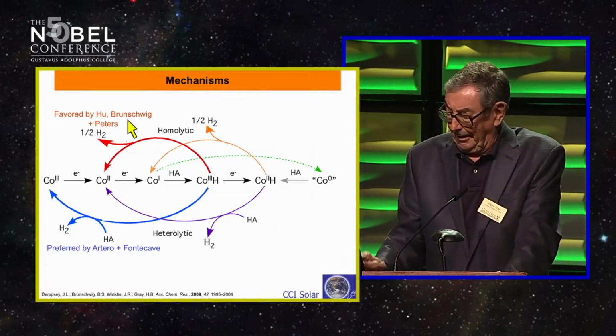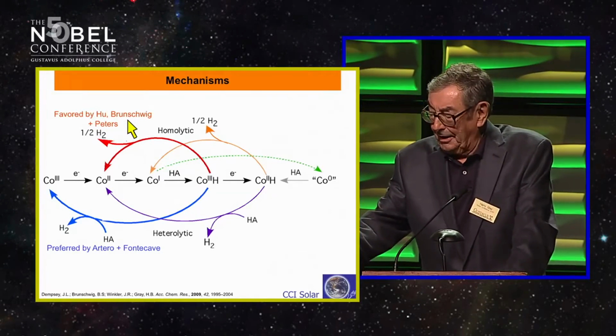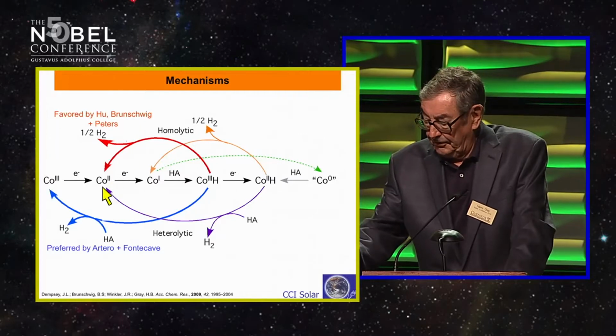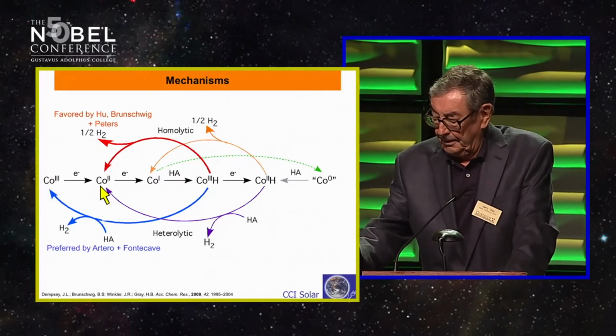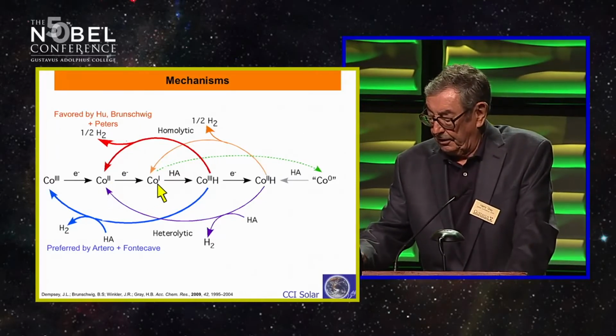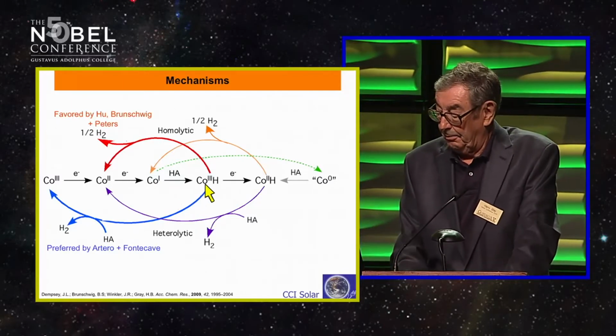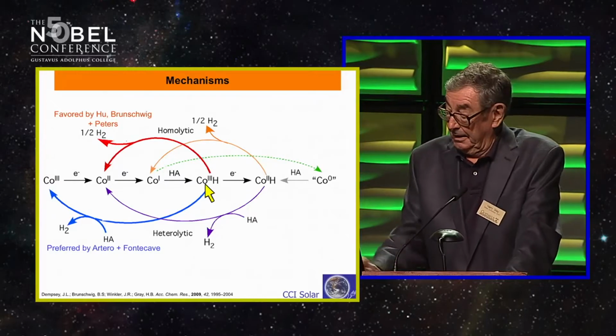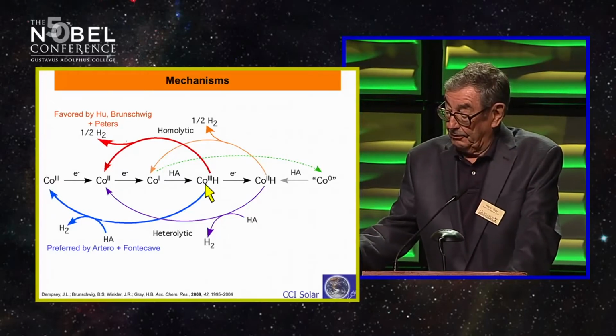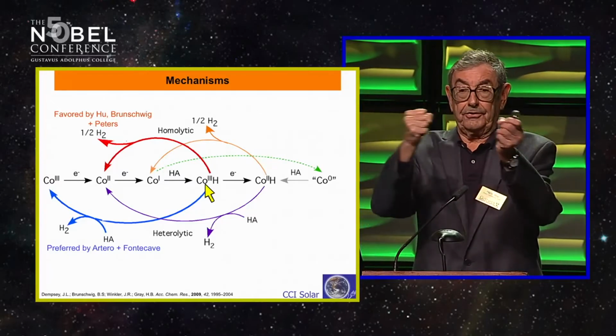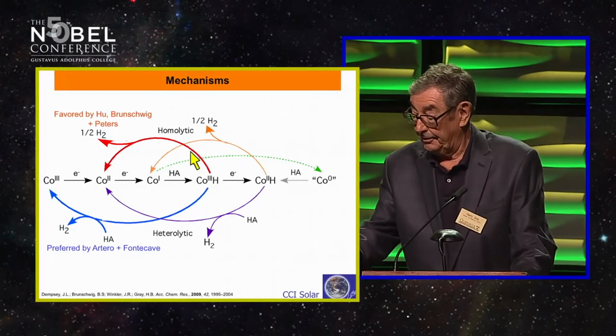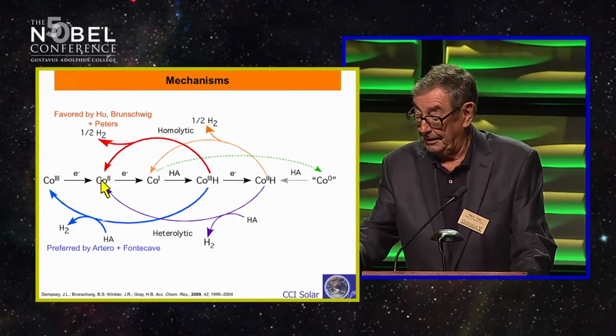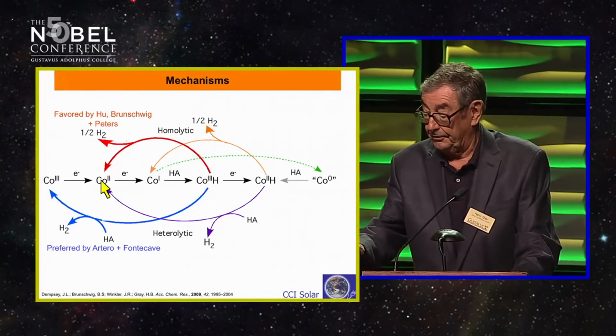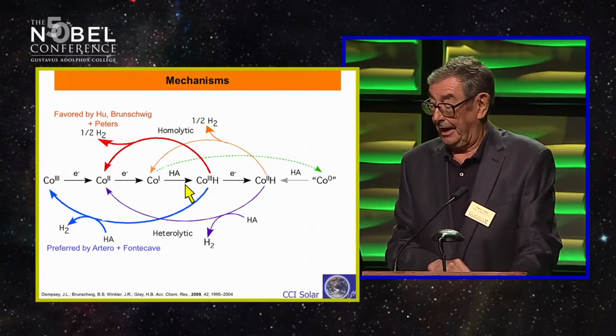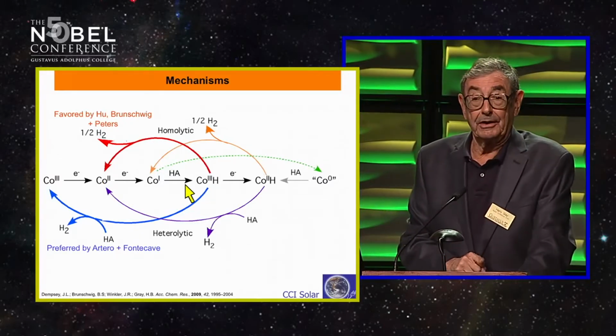Of course, it's France versus US. You would expect that. The American mechanism starts with cobalt-2. At the electrode, it's reduced to cobalt-1 with one electron, picks up a proton to make a cobalt-3 hydride. The cobalt-3 hydride reacts with itself. Two cobalts come together and split off hydrogen in the so-called homolytic mechanism, returning it to cobalt-2 and coming back in this catalytic cycle. That was the American mechanism.